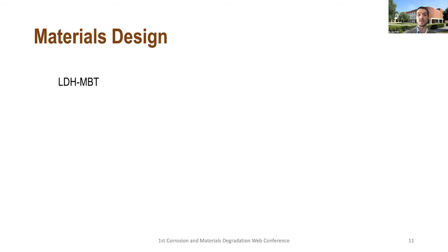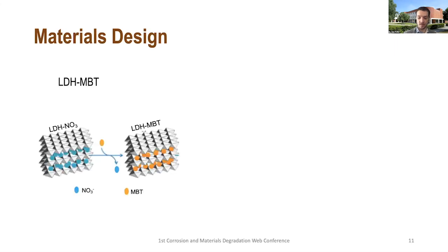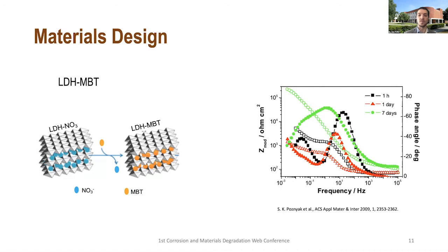Talking about materials design, of course, one of the systems we have studied for a very long time over the years were layered double hydroxides. These are ion exchange clays. And these ion exchange clays are built of positively charged mixed metal hydroxides. And between the mixed metal hydroxides, we have labile anions and water molecules which stabilize the structure. And so a long time ago, we have seen that depending on the inhibitor that intercalates there is a controlled release, and we can actually use this to render active protection to the substrates.